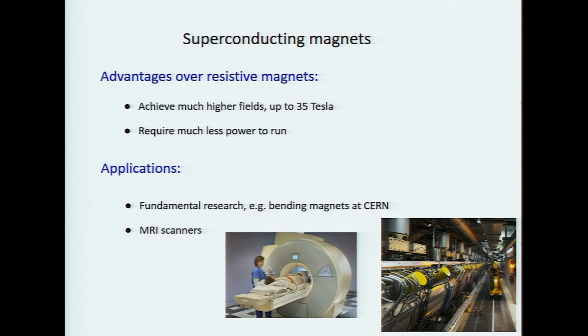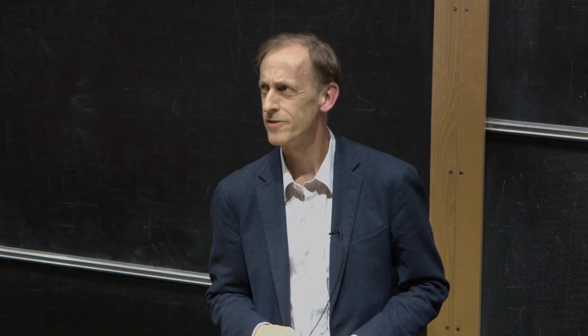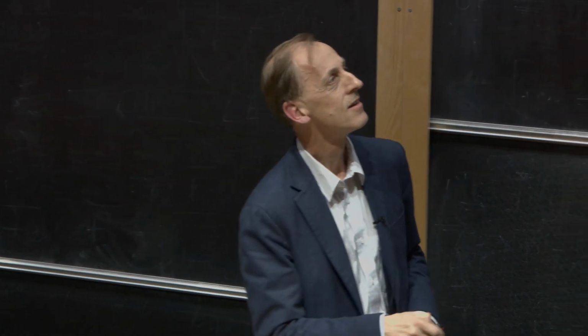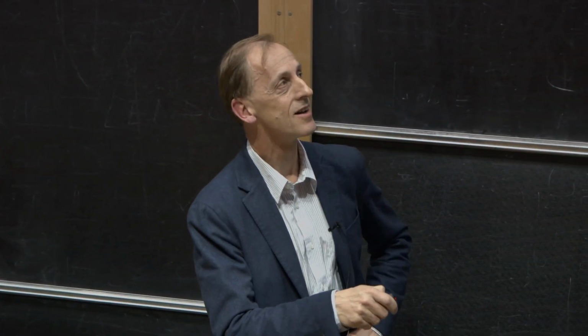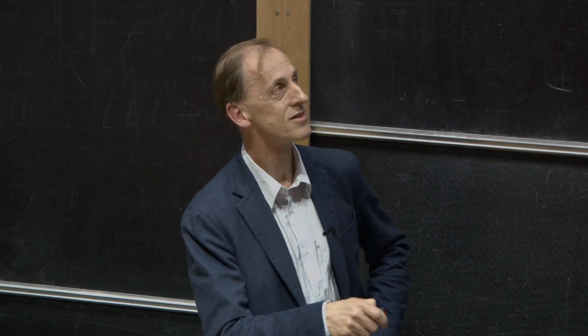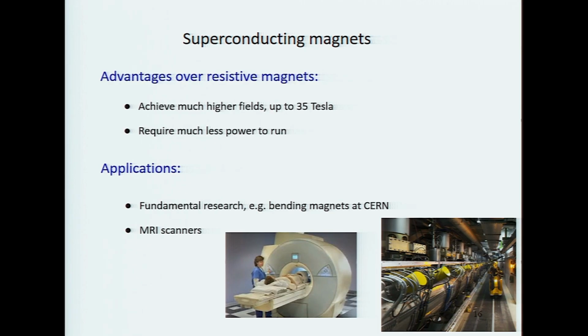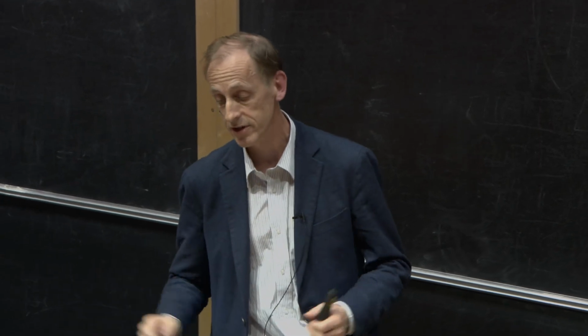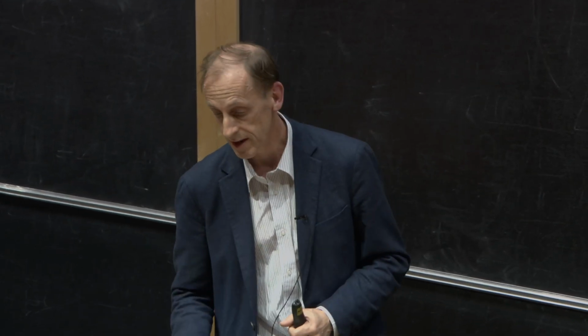And so you roll into here. And yeah, it's very interesting because 1,000 amps is a big current. And if that was to fail and you were inside it... But fortunately, because it remains superconducting, you just don't notice there's any current there at all. These are magnets in the CERN particle accelerator, superconducting magnets all the way around a 27-kilometer diameter ring. And these carry a current of about 12,000 amps. So huge, huge currents, but no power dissipation, so they don't heat up at all. So these are two of the applications of superconducting magnets.